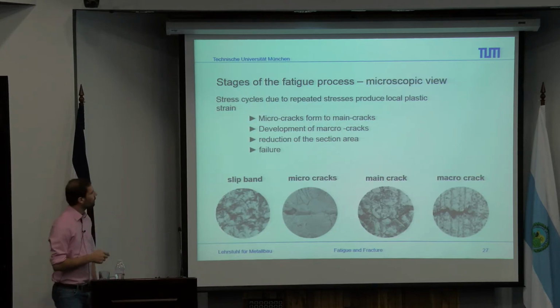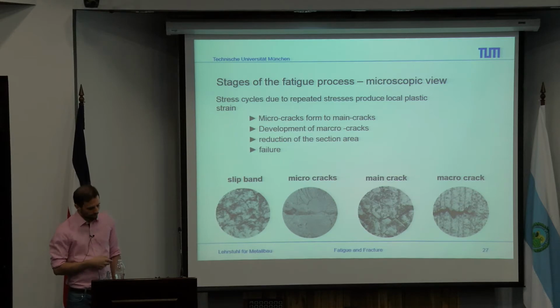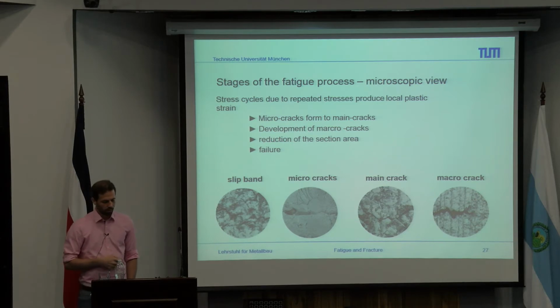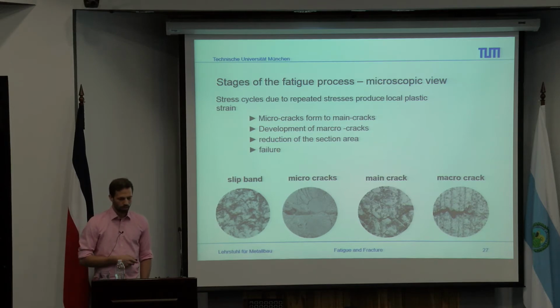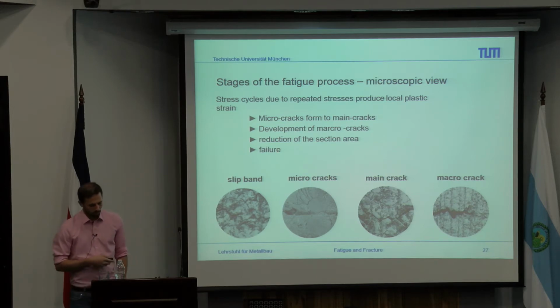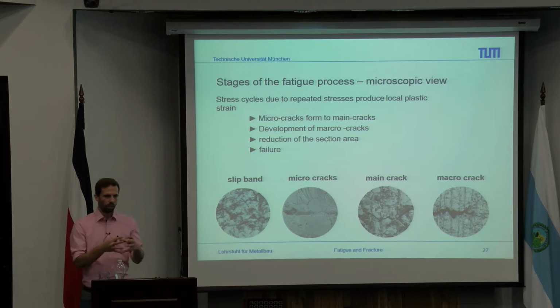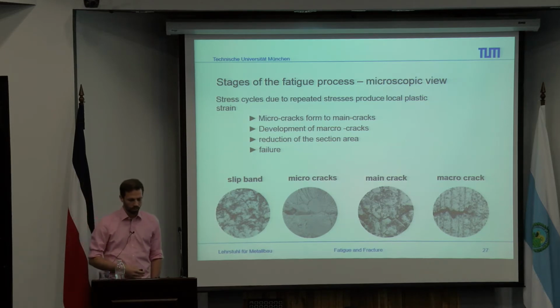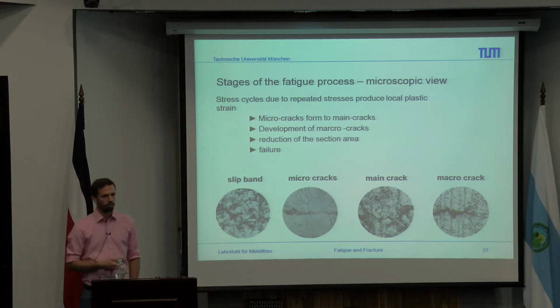So, what are the stages of the fatigue process, which I already mentioned here? We have stress cycles, and due to the stress cycles there occur some local plastic strains. These local plastic strains are related to microcracks that form main cracks. So this is the combination of the microcracks into some larger cracks. Then, as I already said, we have some development of cracks, then the reduction of area, and at the end, the failure.